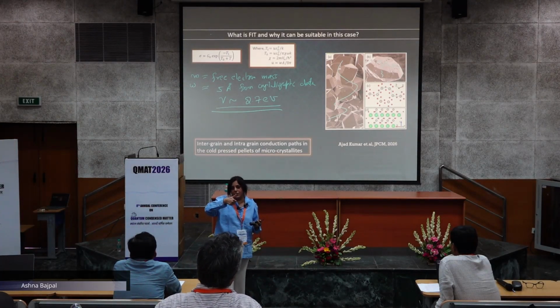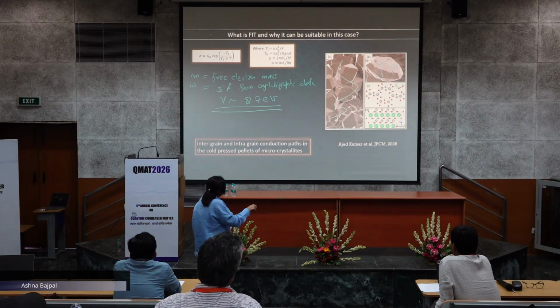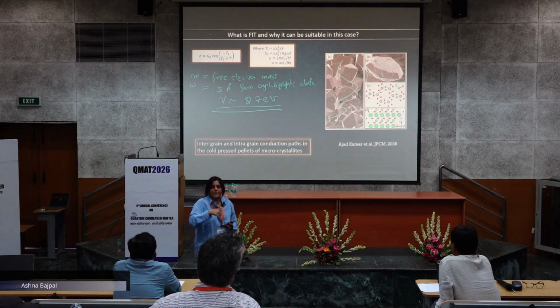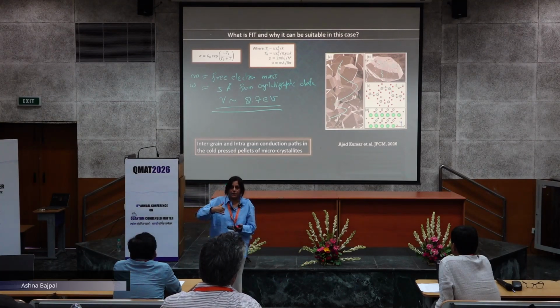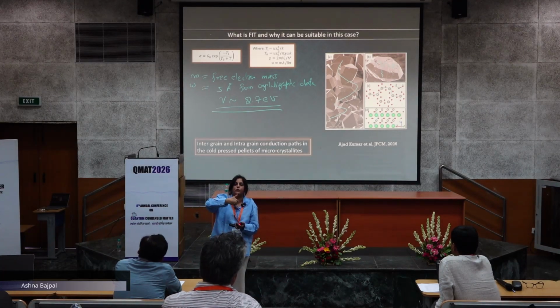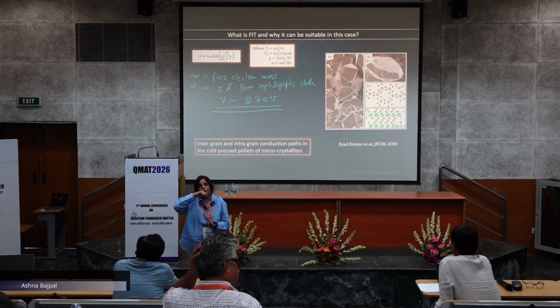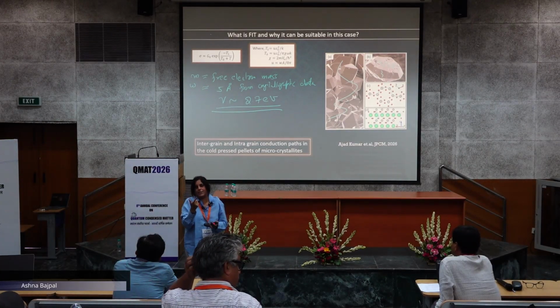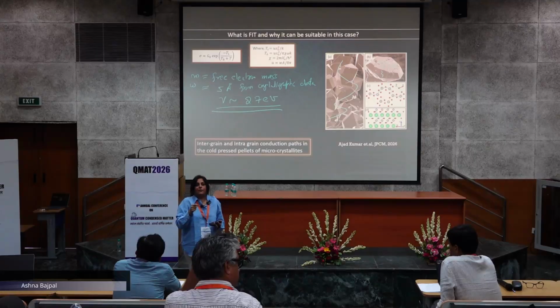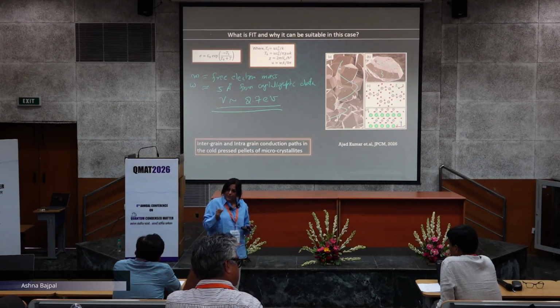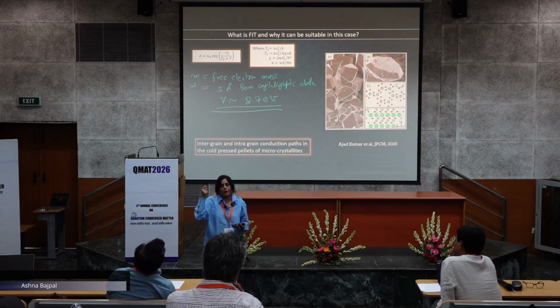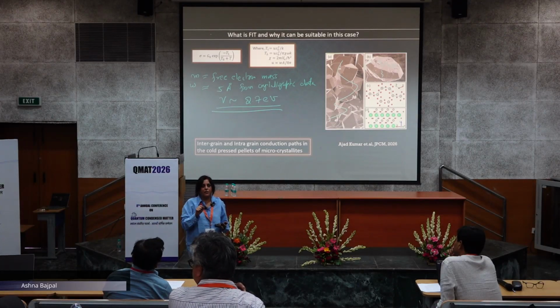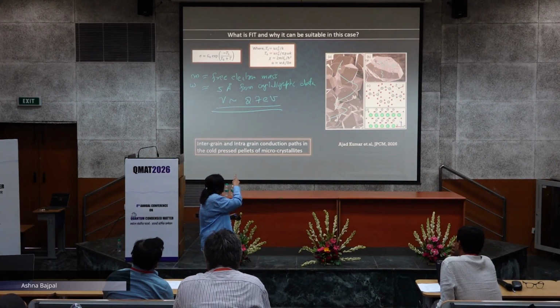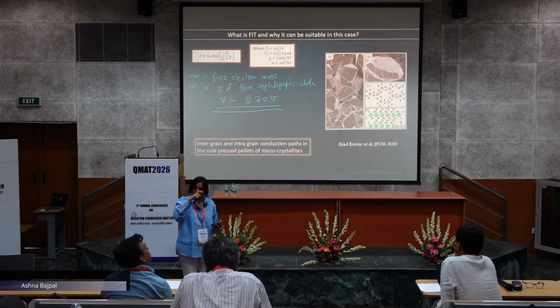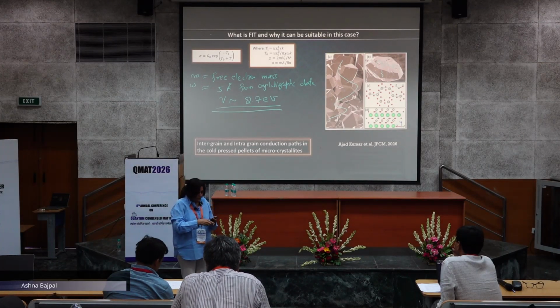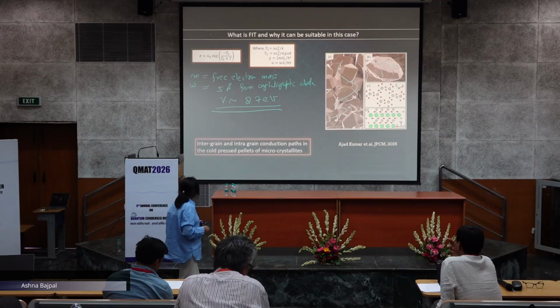So you have a kind of tunnel junction, and you should get MR. What you would need in this case is out-of-plane measurement, so the Z axis, when you see the hexagon. From the C axis, if you do out-of-plane conductivity measurements, you should find these implications of FIT. So we tried making single crystals in collaboration, but we couldn't succeed in making large single crystals. Now we are trying to make out-of-plane conductivity measurements on individual crystallites, which is hard to make because this requires high pressure synthesis.